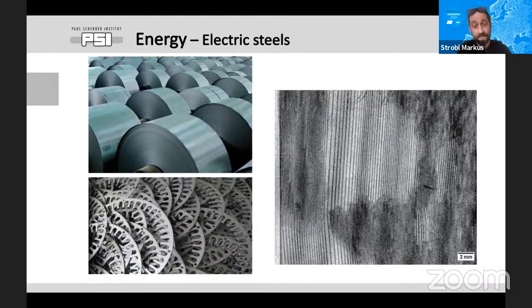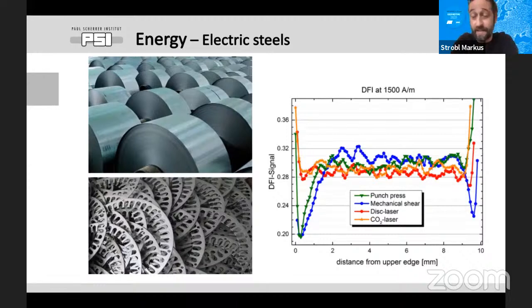And the problem is when you cut this metal, then the domain structure gets disturbed where you cut them. And what we did was basically to qualify different means of working them, of cutting them, from bench pressing, mechanical shear, to lasering. And you can see that there is a big advantage of the lasering. And there was work for companies going into optimizing the lasering in order to not destroy the domain structure at the edges, which leads to significant energy losses.